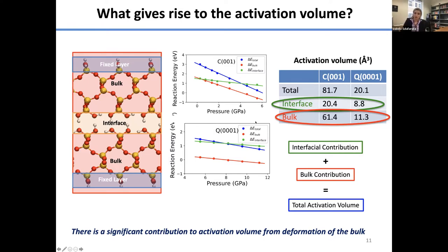And here are the results. So this is showing our reaction energies for the two cases I showed you earlier. The total energy is the blue, and now the contribution from the interface is the green one, and from the bulk is the red one. And again, the activation volume, or mechanochemical coupling, is the slope of these, and they're calculated here in the table. And lo and behold, you can see that the bulk contribution is not only significant, but actually in some cases is dominant. And so what it means is that mechanochemical coupling for these sliding interfaces under pressure is not necessarily controlled by stress-induced changes in the interfacial groups and the molecules that are trapped at the surface, but by the stress-induced deformation of the surrounding bulk. So the properties of the surrounding bulk matter. And in fact, in some cases can be dominant. So we found it surprising because it's different than what people typically believe. And let me show you the consequences of that.